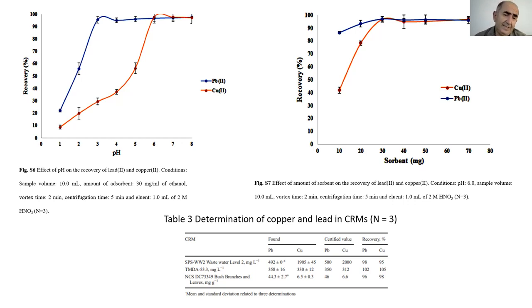For example, as you can see here, the effect of pH is investigated. Also, after optimizing the pH, we optimized the amounts of sorbents. Then we applied our methodology to certified reference materials for the validation of the methodology. We can get quantitative results for the certified values. Then we apply our methodology to real samples, including water and food samples.